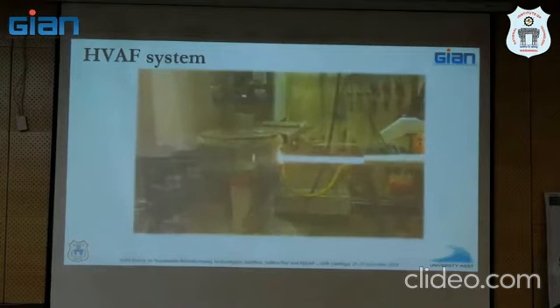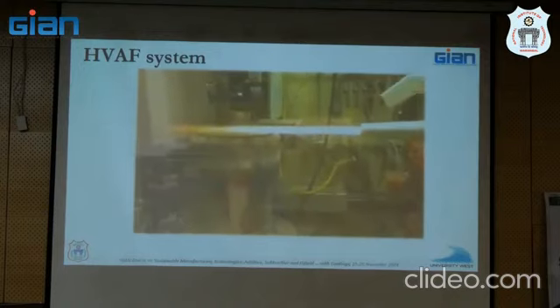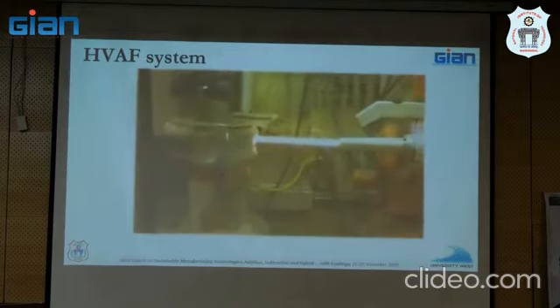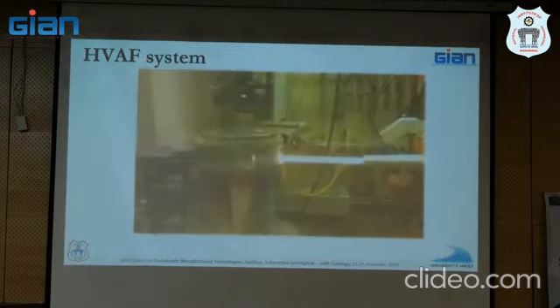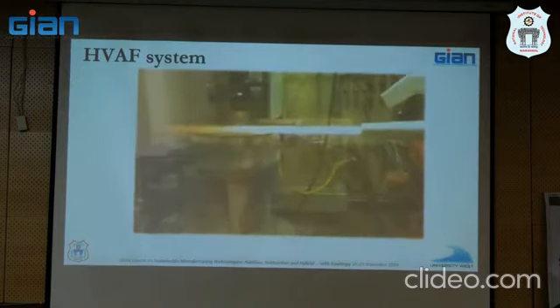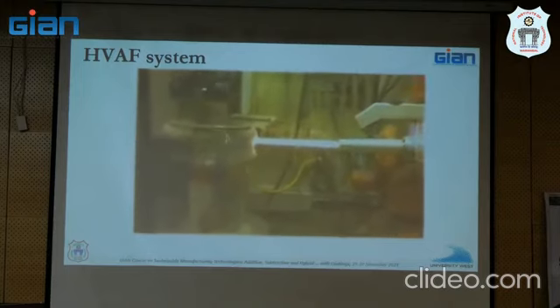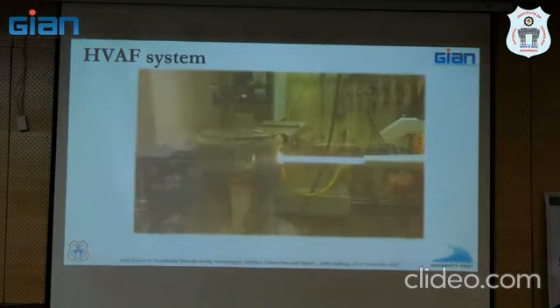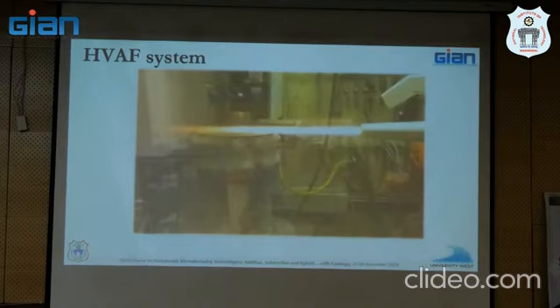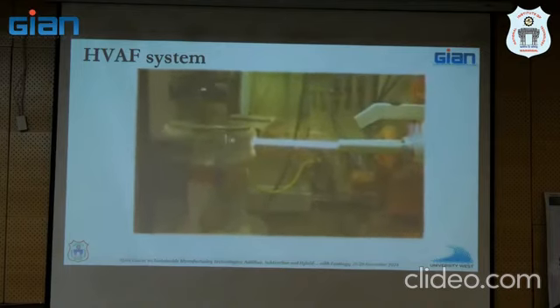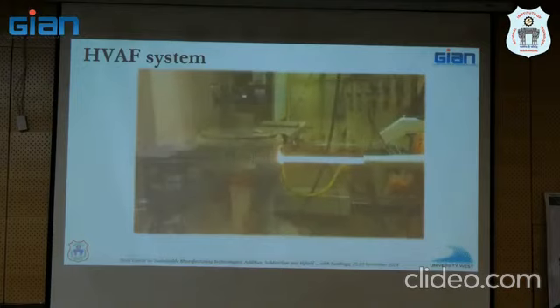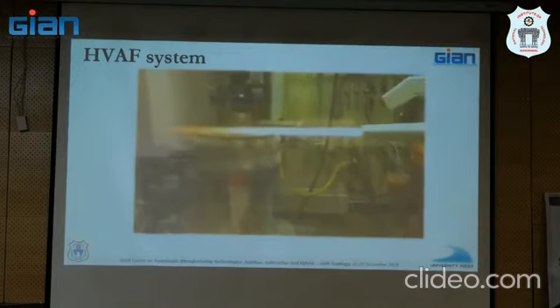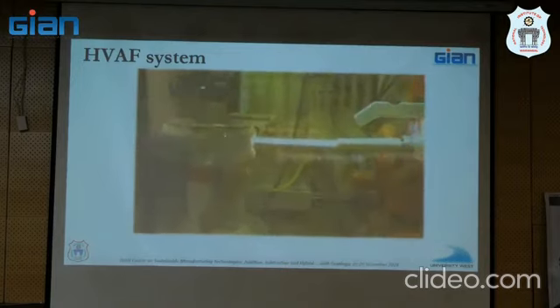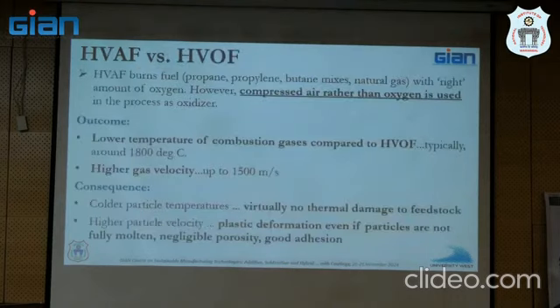Yeah. This is a high velocity air fuel system from my lab. Looks very nice, doesn't it? Right? Very stable flame. We use this mostly to spray tungsten carbide, and this will give you an idea of how high the productivity is. Beautiful flame. We put on almost 10 to 20 microns per pass. Every time that goes around, you build 20 microns, so it's pretty quick. Yeah, in about 10 rotations, you build 200 microns on whatever part. So that's a big advancement.